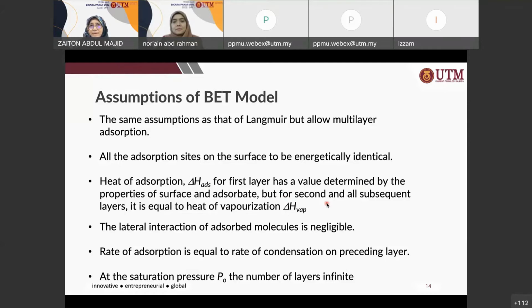That's why for nitrogen, for example, the experiment is run at 77 Kelvin, which is the condensation temperature of nitrogen, liquid nitrogen. Fourth assumption, the lateral interaction of adsorbed molecules is negligible. They do not interact laterally. The rate of adsorption is equal to the rate of condensation on the preceding layer. So for the second, third, fourth layers, the rate will depend on the rate of condensation of the gases. And at the saturation pressure P0, the number of layers is infinite.